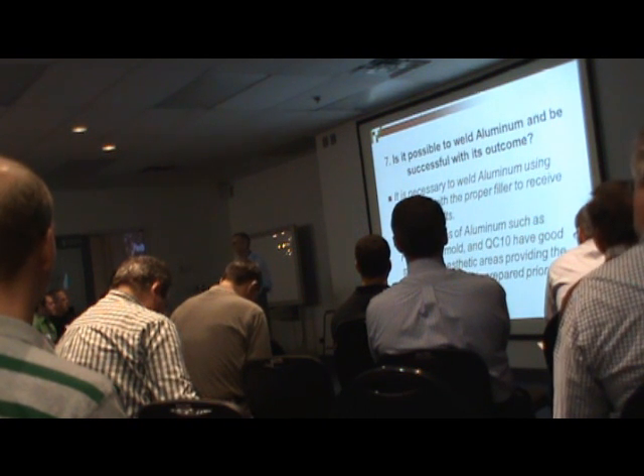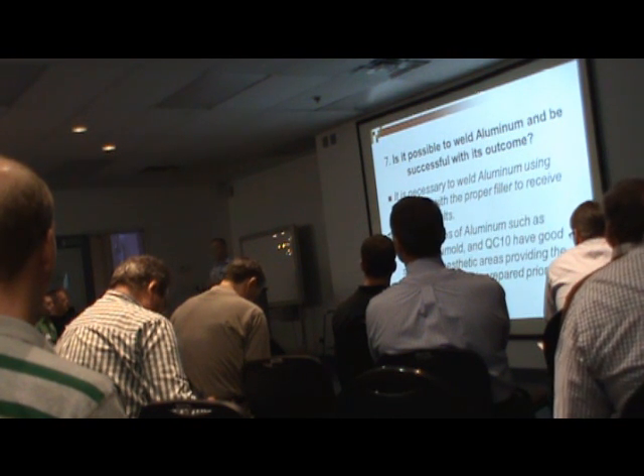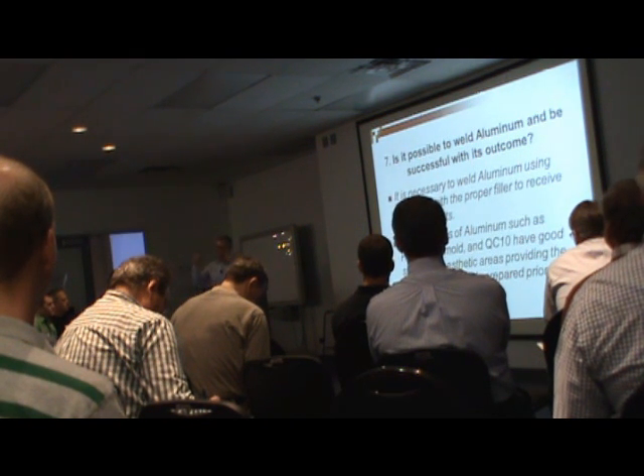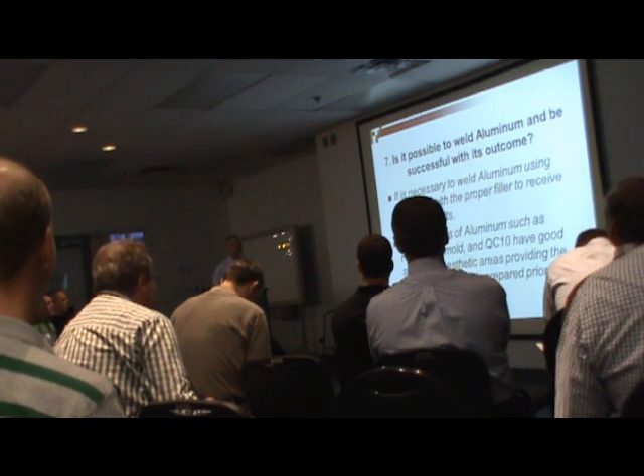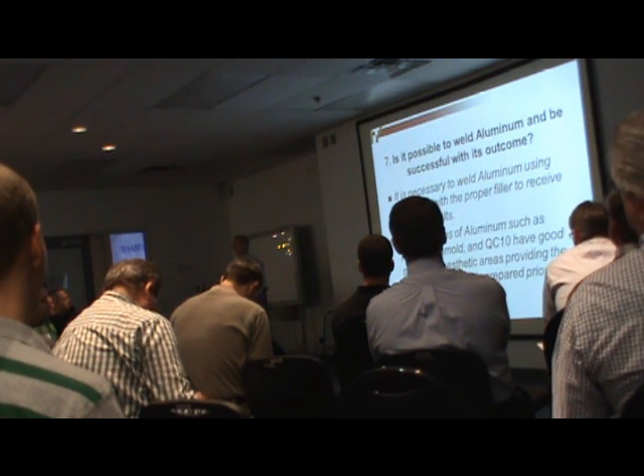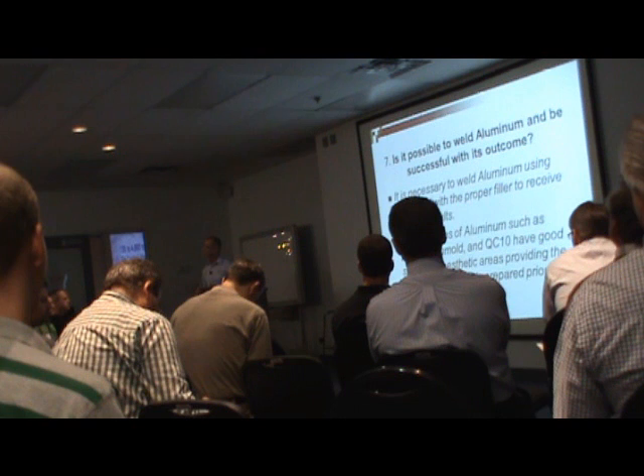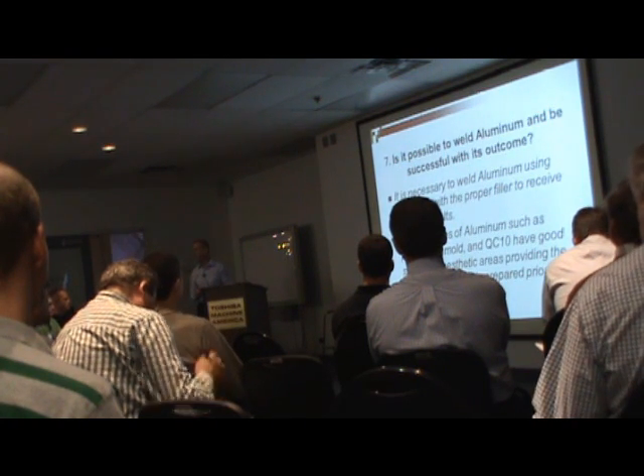We will weld it in areas of 7075 that are not in an aesthetic area. But if we know we're going to go with a Class A surface, we're not going to choose that material. We're going to choose something else. Of course, we don't like to weld, but mistakes do happen, whether it's in the tool-making side of it or in the process side of it. So, again, the experiences have been fairly successful as long as you're using an experienced welder and they're using the proper rod and they are preparing the aluminum correctly to weld. So it is very successful to do this.